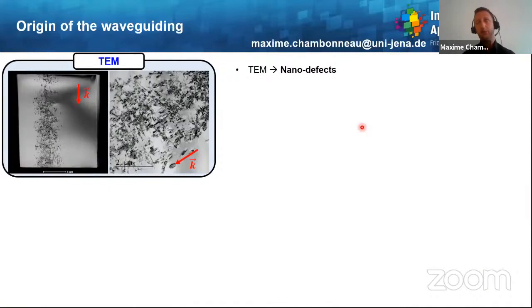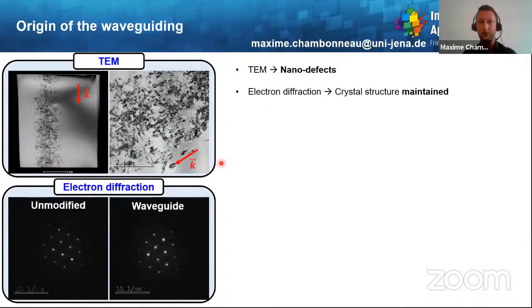To answer this, we relied on nanoscale characterizations, especially with TEM, so transmission electron microscopy. And as you can see here, it is possible to image some nano defects along the waveguide track. Okay, what now about electron diffraction? Well, this we have carried out. And as you can see here, there is no drastic change in the crystal structure. So the crystal structure is maintained, but still we see under bright field TEM that there are some defects.